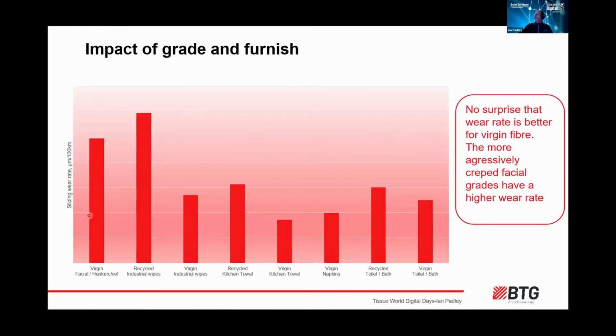Let's look at the impact then of grade and furnish. This is across all high-performance blade types. And no surprise that the virgin fiber furnishes tend to give quite low wear. One little outlier on that here is the virgin facial and handkerchief grades, where we crepe quite aggressively for softness. These will tend to have a slightly higher wear because that aggressive creping maybe requires quite a harder coating.